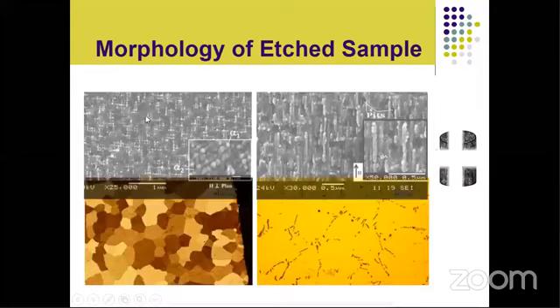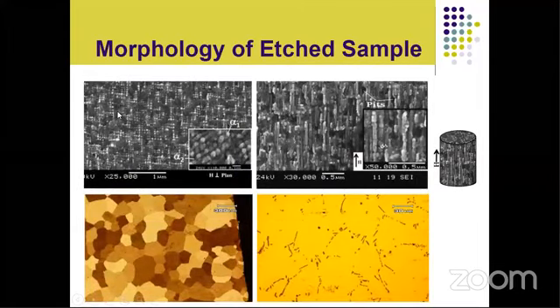At higher magnification, these are the field emission scanning electron micrographs taken along the field when the field was applied and perpendicular to the field. If this is the magnet, you can see the field was applied in this direction, from bottom to up. So when the field is applied along the length direction and the material is observed from the top, you can see fine rods. This material was actually etched in an acidic solution. And this inset shows the higher magnified view.